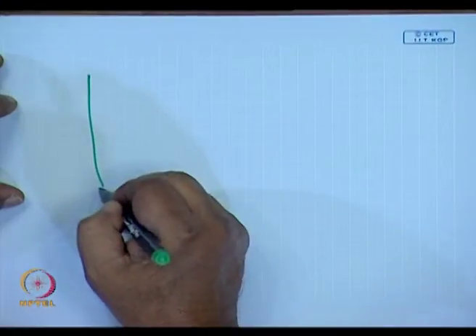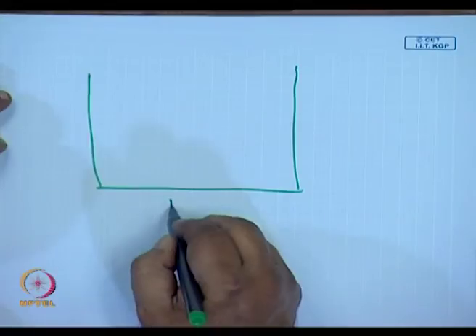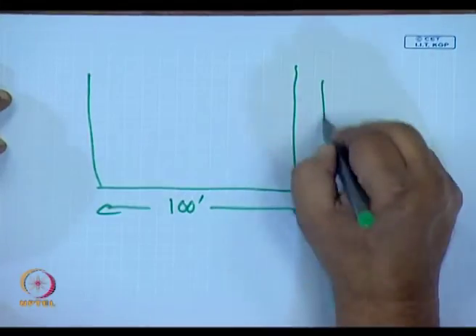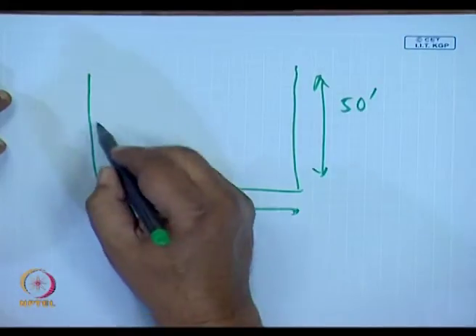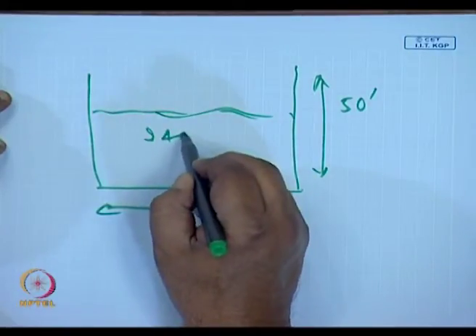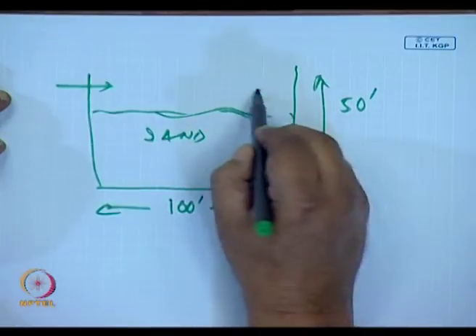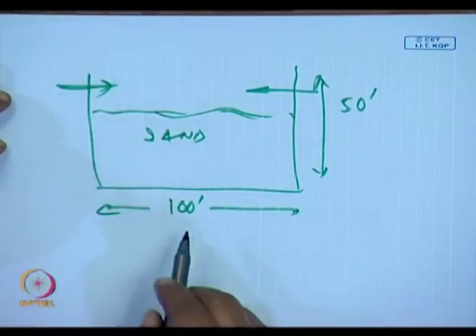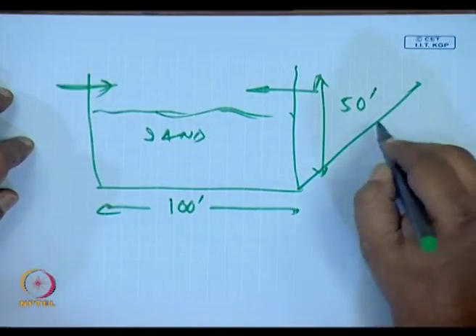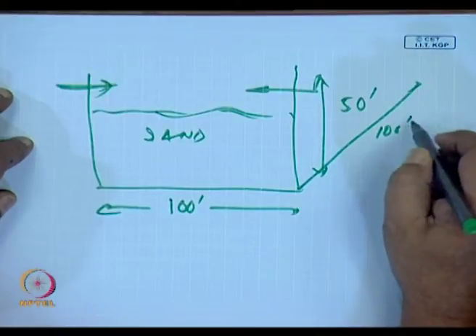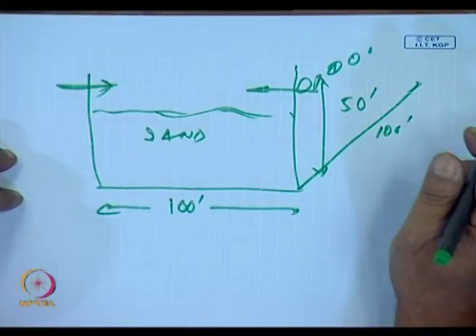an offshoot of industry, because in, say, glass melting furnaces, what they do is, schematically say showing, they have huge tanks, 100 feet, 50 feet high. This has all the sand and other materials, and they used to have burners blowing from the sides. The length would be anywhere up to 100 feet. So they had lots of burners which were needed to melt this material.